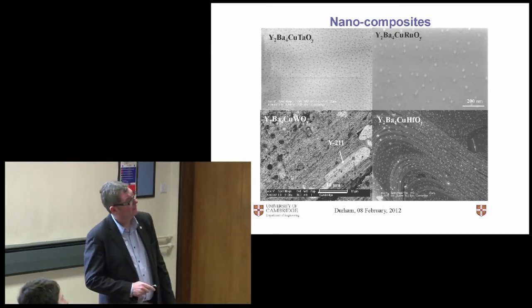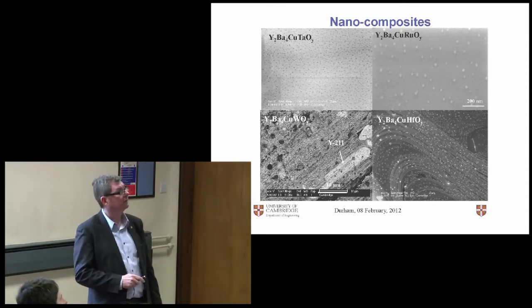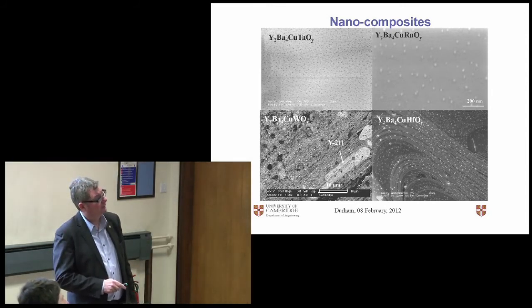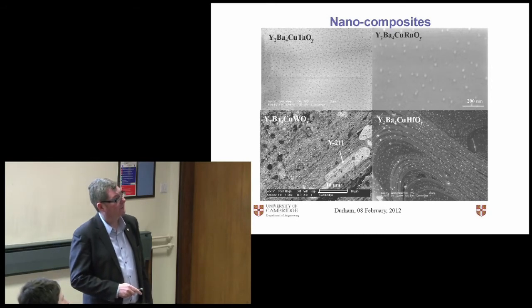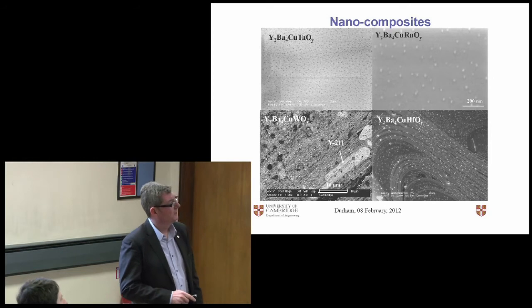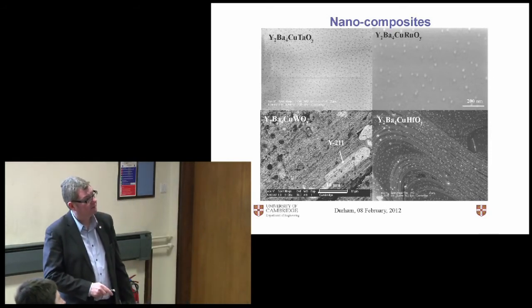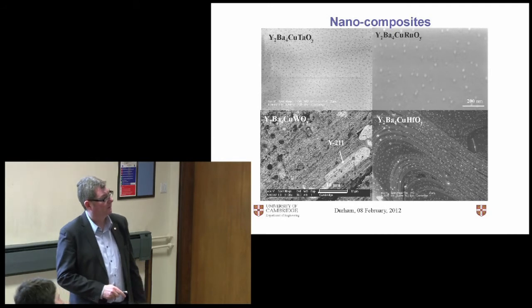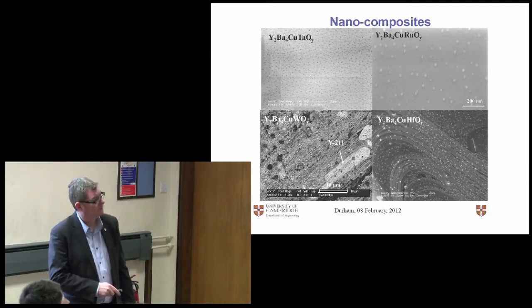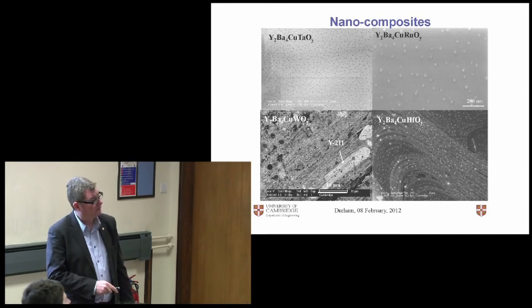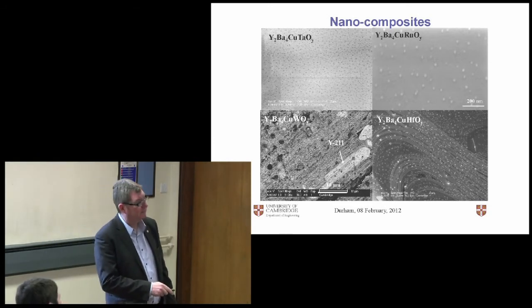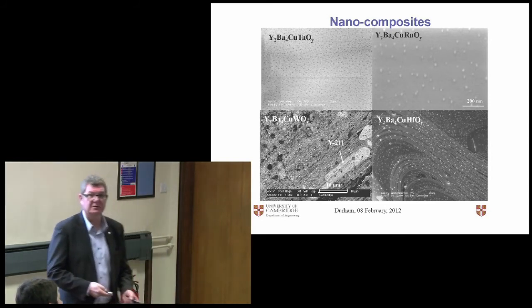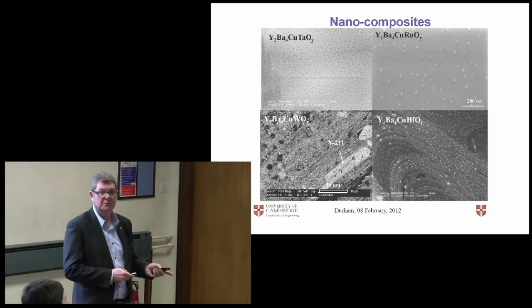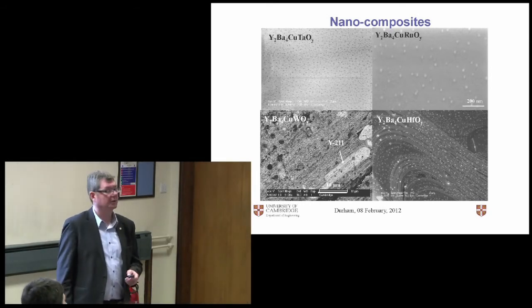So here's the tantalum variant. Again, these very fine dots are the 211 tantalum-based pinning phase. Ruthenium, again, it's a very nice array of second phase particles. Hafnium, this is along one of the facet lines. Again, these tiny dots are the 211 phase. And I think the tungsten one is the most telling one. Here's a 211 particle, and you can see the tiny dots, smaller than the dot of the laser pointer, are the 211 phase. So that gives you a graphic illustration of how you can engineer pinning sites if you use sensible inclusions rather than try to work for 211.